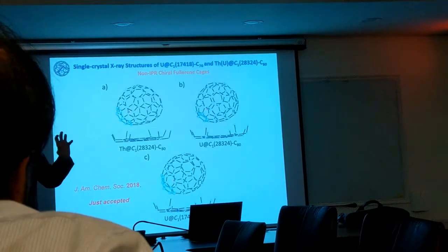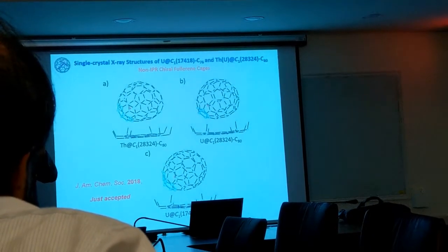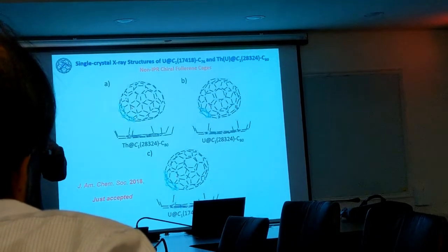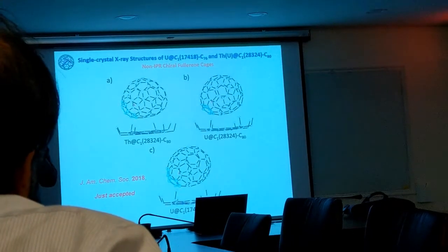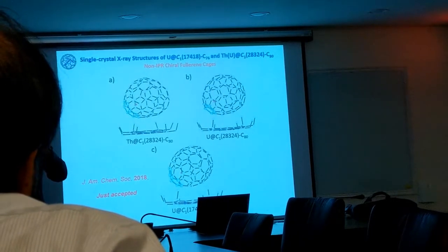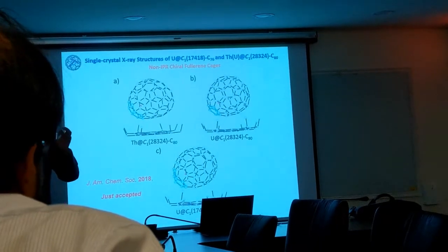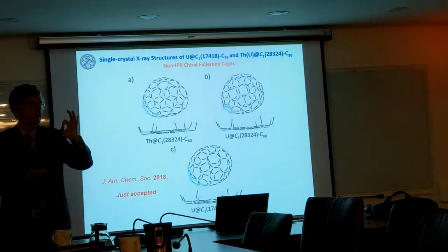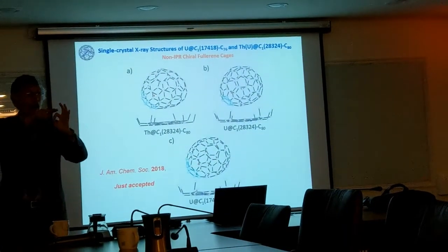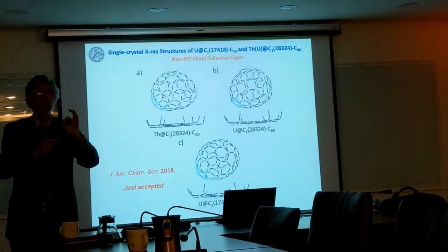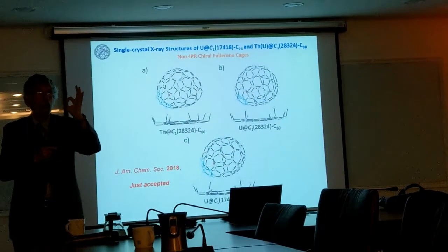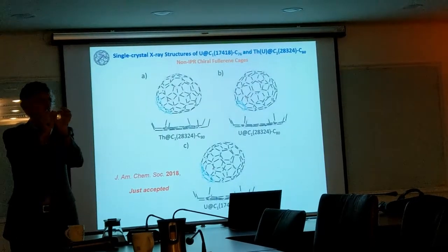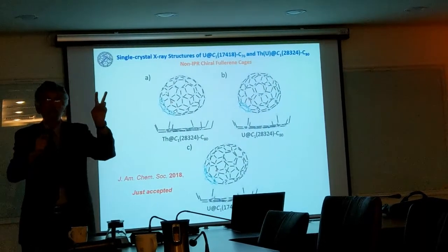When you deal with empty fullerenes, there are no known exceptions, except when functionalized from outside or from the inside, to the so-called isolated pentagon rule. That means that pentagons on the surface of an empty fullerene are always adjacent to 6-member rings. So 5-member rings are isolated from each other. You never see 5-5 fusions. Clear? So now you know two things.